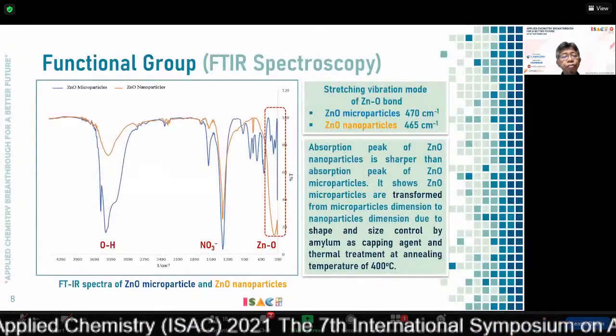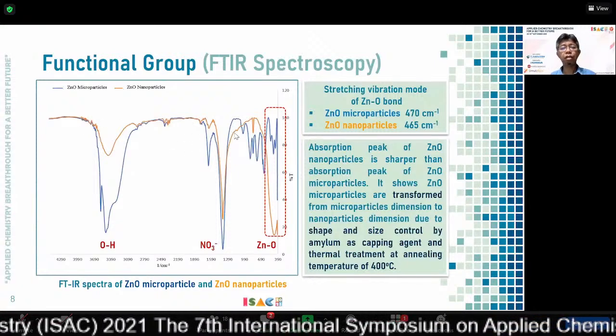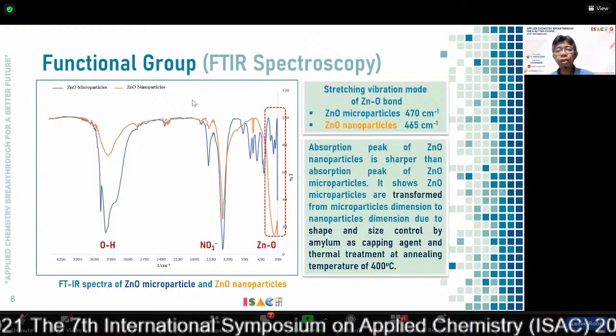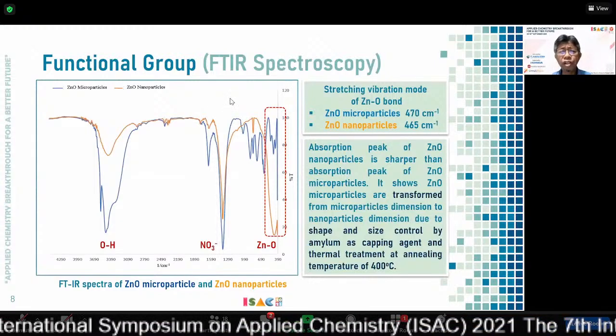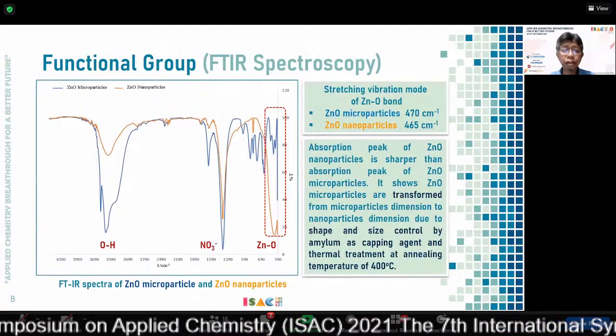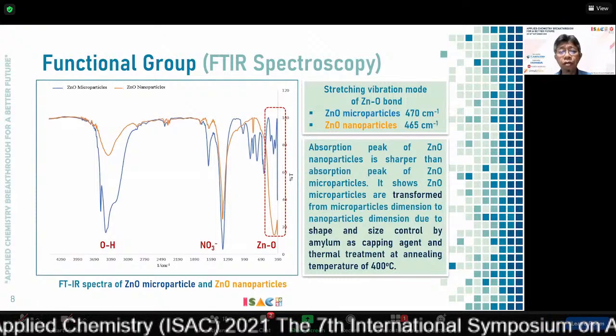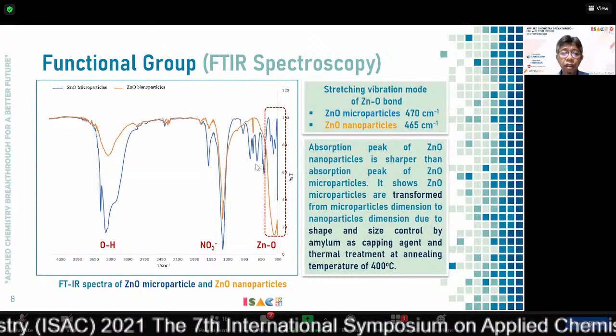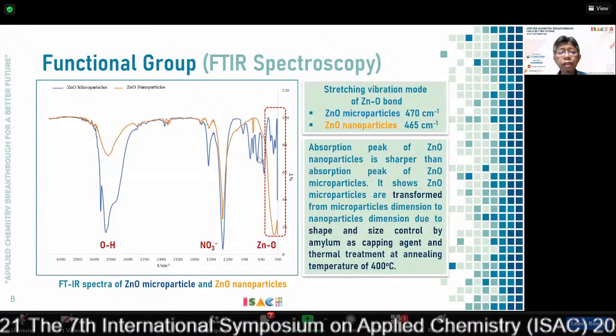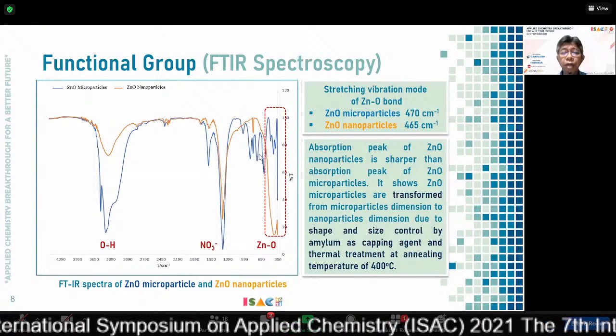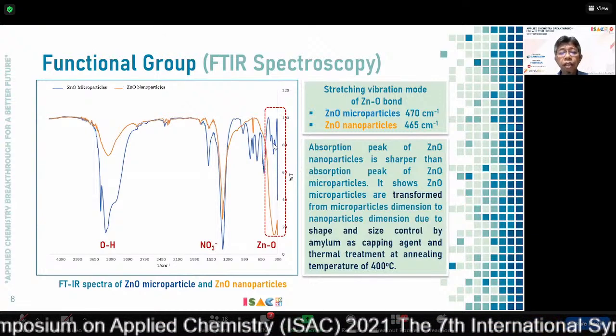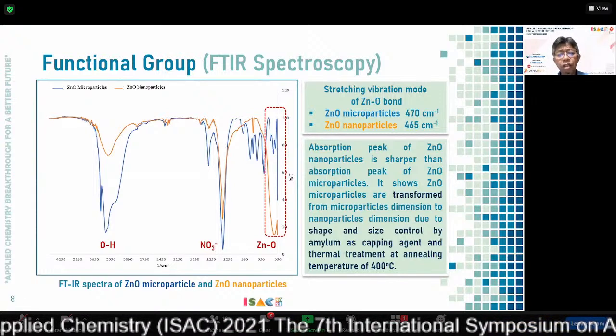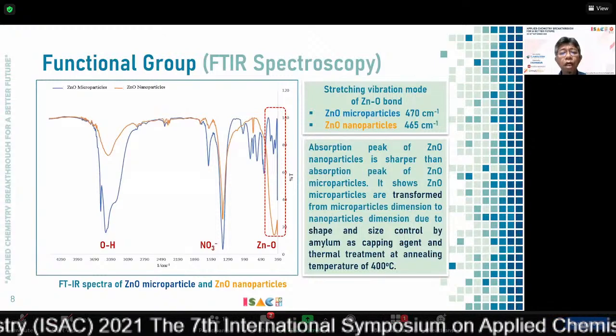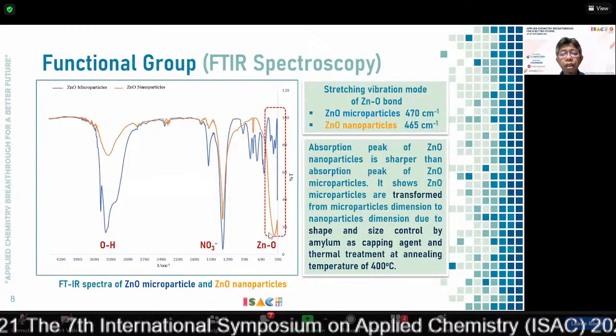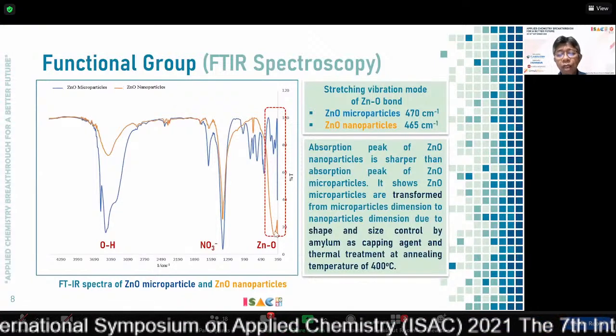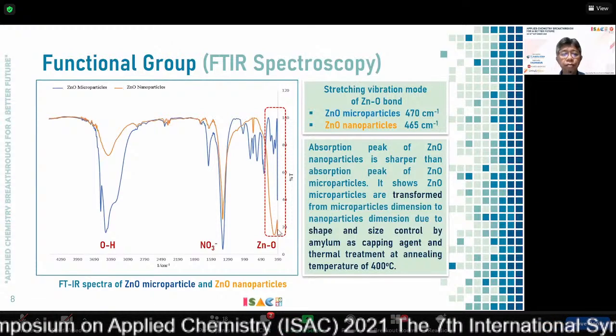And if you look at the functional groups, they are mostly for the metal oxide. The stretching vibrations occur below 1,000 per centimeter, and particularly for zinc oxide, usually around 500 per centimeter. So here, if we look at the brown spectrum that belongs to zinc oxide microparticles, the zinc and oxygen bond stretching vibration occurs at 470, while for zinc oxide nanoparticles it is about 465 per centimeter.